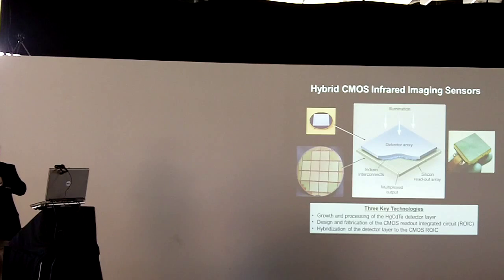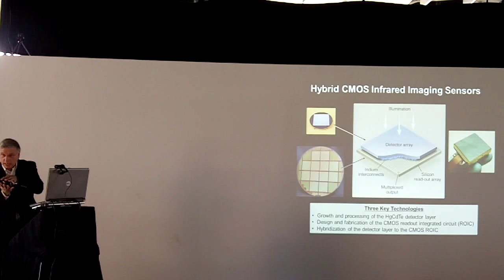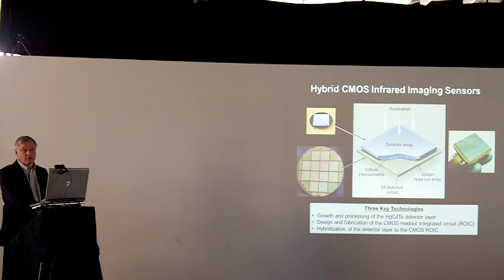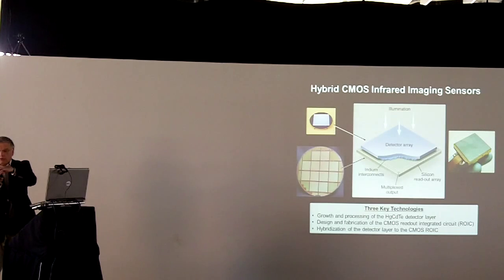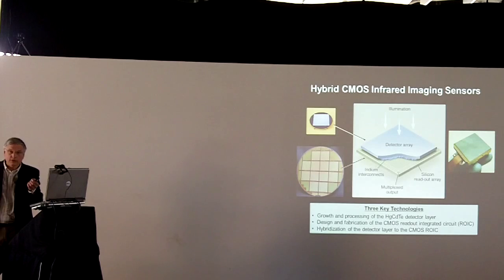Each pixel is only about 18 microns across. So that's 1/5 the diameter of your hair, and you've got to line that up just right, those bumps. Push it down hard. I'm not allowed to tell you exactly how hard you push it down, but it's about 4 of us standing on it at one time. That's about how much pressure you have to put on, and you can't let it slip while you're doing it. So hybridization is part of the trick. Now when you grow the detector layer, you only grow for the wavelengths that I just showed you there, about 5 to 7 to 10 microns thick of material. But the crystal lattice you start with, this Cad-Zinc-Tel wafer here, is about 500 to 700 microns. So you grow the crystal lattice here, you pattern in, you put indium bumps, you flip it over, you put it down on your readout circuit, and now the light has to come through the Cad-Zinc-Tel substrate to get to where you actually want it to get. So you've got 500, 700 microns of Cad-Zinc-Tel and just a little thin layer of mercury cadmium telluride.